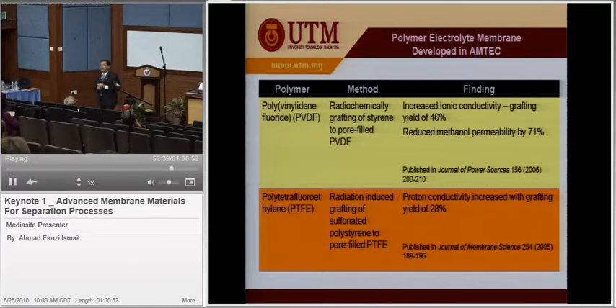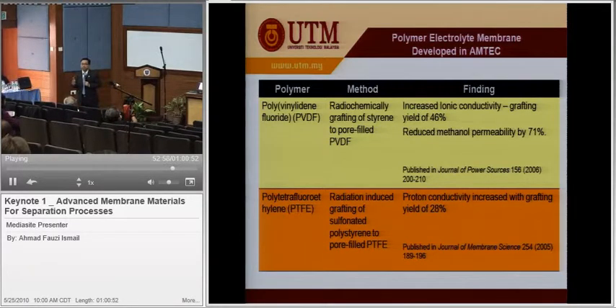In terms of fuel cell material development, we use polymer. This is a method, radiation grafting. And this is our finding, which was published way back in 2006 from our lab. The grafting yield is about 46%, and we can reduce the methanol permeability, the loss of energy, by 71%.